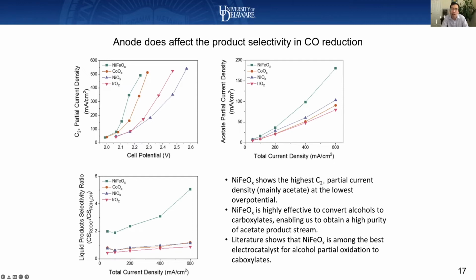This is not that surprising because people report nickel iron actually is better than iridium in alkaline environment for OER, oxygen evolution reaction. But if you look more closely at this acetate partial current density on the right, what you find is the acetate partial current density for nickel iron catalyst is way higher than iridium oxide. If you take the ratio between alcohol production and acetate production, you will find all three, iridium oxide, nickel oxide, and cobalt oxide, are more or less similar. Only nickel iron oxide stands out.